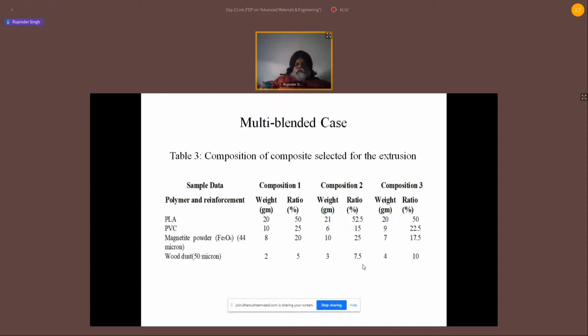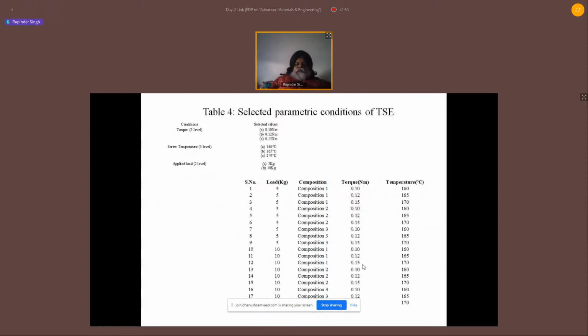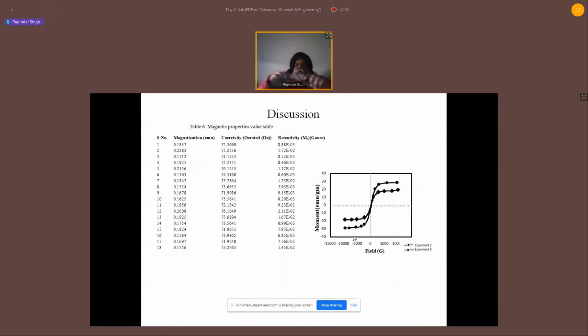So we try to observe the different compositions, and then we work with different torque available on the extruder, then their temperature, then the load condition, and we use a DOE, and we prepare the different feedstock filament. Then we did a VSM, vibrating sample magnetometry test, to understand whether my material really has a good magnetic property.